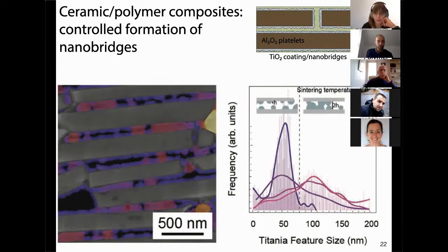So what works for us there is that the contrast of this interface is very different from the rest of the composite. So by image analysis, we're able to separate the interface here, and we're able to measure the local thickness. And what we can see is that we have a nominal thickness of the coating here that is around 50 nanometers. But as soon as you start bridging these two layers, you start measuring effectively larger thicknesses. And so by plotting this distribution of thickness, you can see that as we increase the temperature, we form more and more bridges. And so just by getting the fraction of bridges that are larger than a certain limit, we can say, okay, this one is a bridge, or this one is just the normal coating we had before.